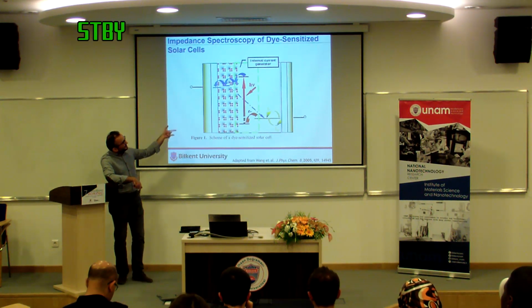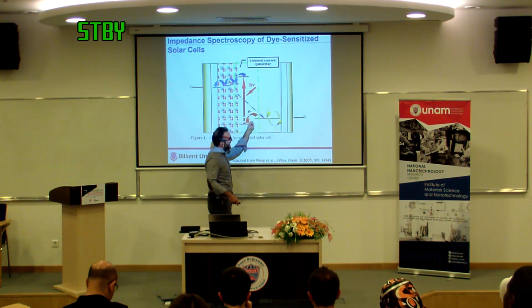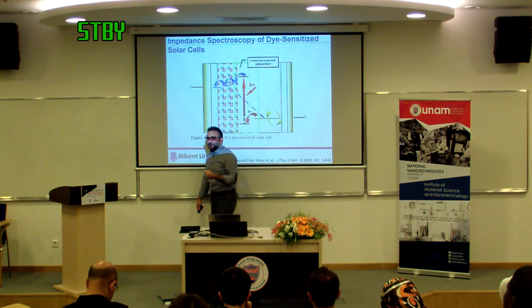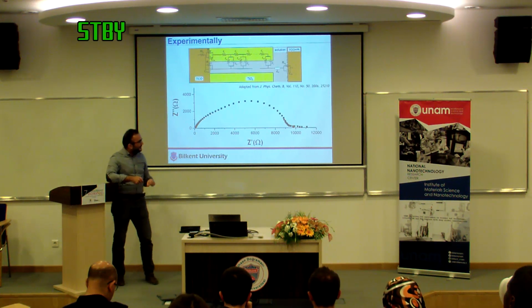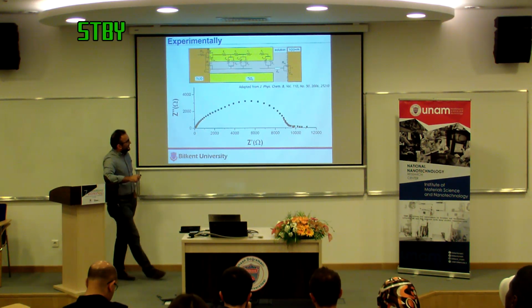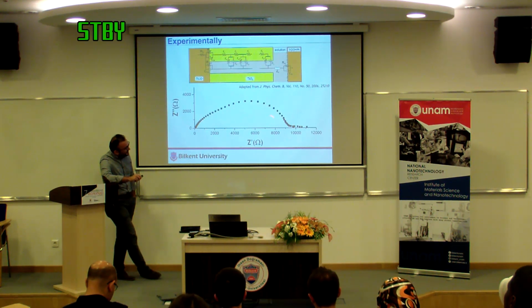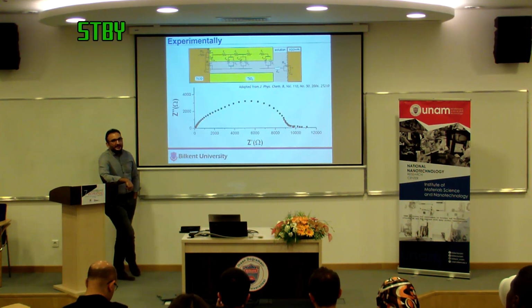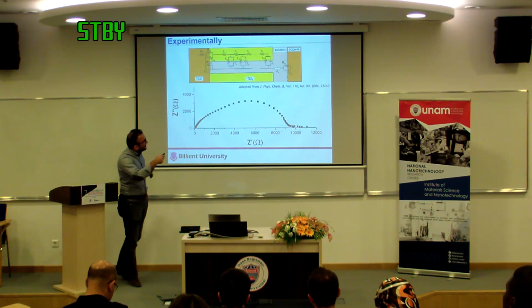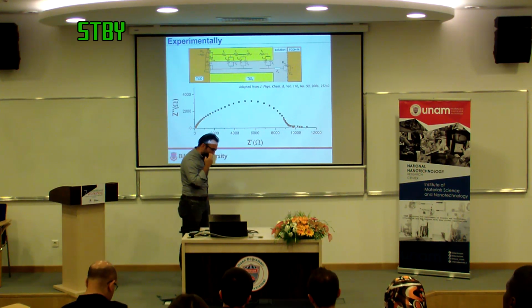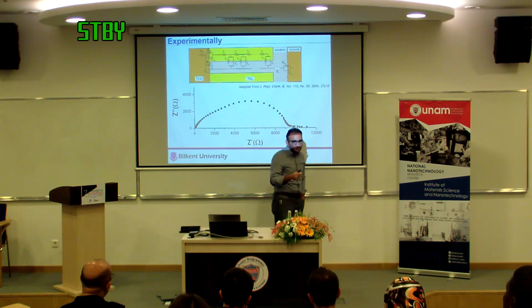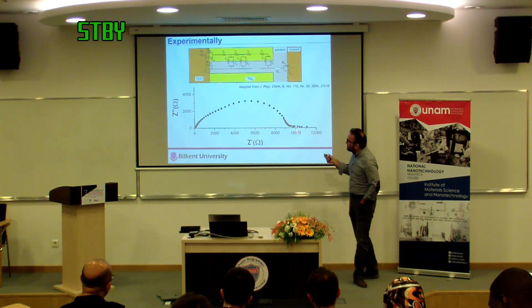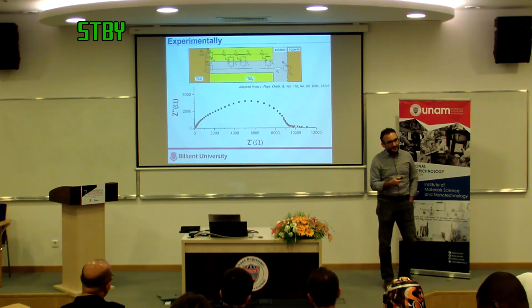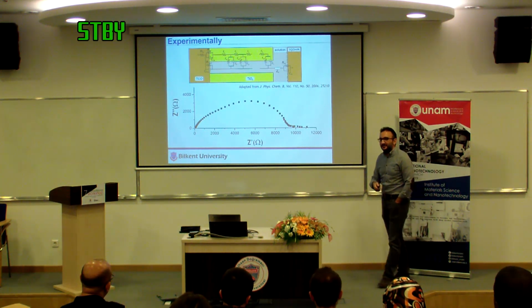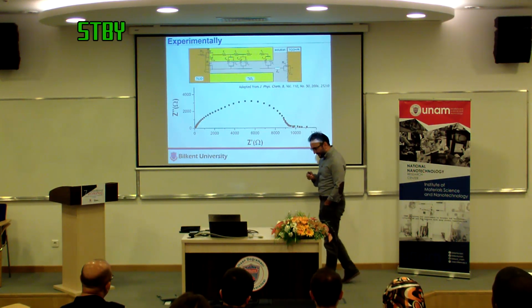Because of this many interfaces, there's the titanium, there's the dye, and there's the counter-electrode, the impedance spectroscopy of these things is very rich. Here is some typical data, and you see that the data has quite a number of kinks and turns and bumps. The typical model in the literature for this is this. Now I'm going to skip the details of the model for now. I'm only going to say that this is a 15-parameter model. And though the data is rich, I don't know that there are 15 degrees of freedom there. I don't know that I would trust a 15-parameter fit, even if the data is this rich.